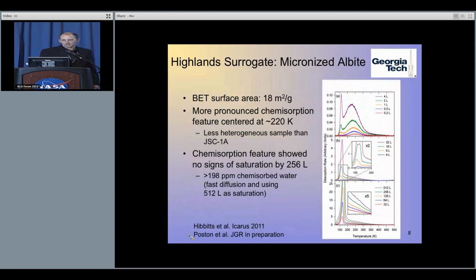Similar analysis for the Highlands surrogate. We still see ice, and then we see a narrower distribution of these, what I'm interpreting as chemisorption sites, which makes sense because the albite is a much less heterogeneous sample than the JSC-1A. And then down at the inset again, we don't see any apparent saturation on the albite, even up to a much larger exposure than we used on the JSC-1A.